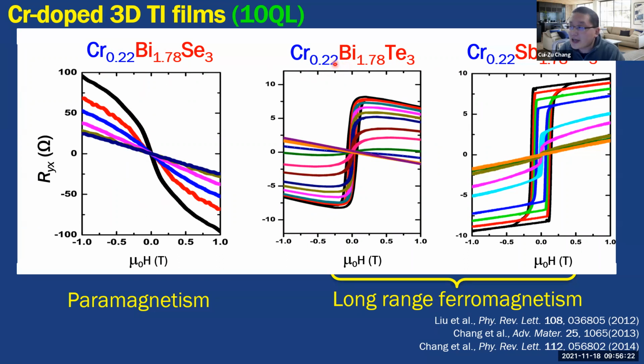So the good news here is chromium-doped bismuth telluride and chromium-doped antimony telluride, both of them are ferromagnetic. And at low temperature, it shows the ferromagnetic hysteresis. And there is another good news: this one is N-doped and this one is P-doped. As I just showed you, the third step for the realization of the quantum anomalous Hall effect, we need to reduce the carrier density to make it in the insulating regime. So here, we choose these 2 materials as the candidates for the realization of the quantum anomalous Hall effect.